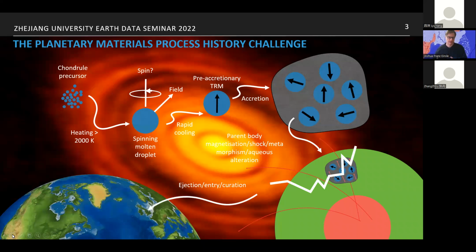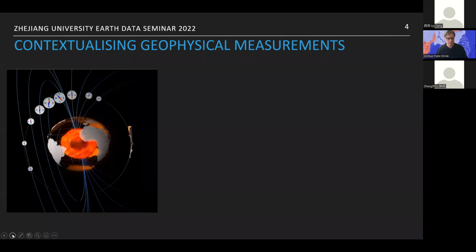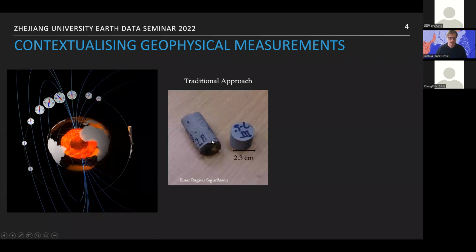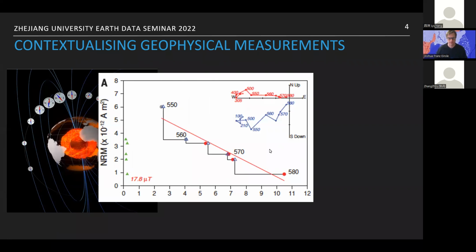And so throughout all these steps, we've had a very elaborate materials processing history where materials have undergone changes, mineral transformations, shocks, deformations. All of these leave their traces in one way or another on the sample. And we need to try and backtrack from these very small samples to the physical processes that led to building them, and how we understand planetary evolution in the early solar system. Another way to think about what we want to do is to take a geophysical measurement, which is usually large in bulk. In paleomag, that means taking a 2.3 centimeter core like this and doing a demagnetization of it, a Zijderveld plot for example, whereby by thermally demagnetizing the sample, we can hopefully understand the direction and magnitude of prior magnetic fields.